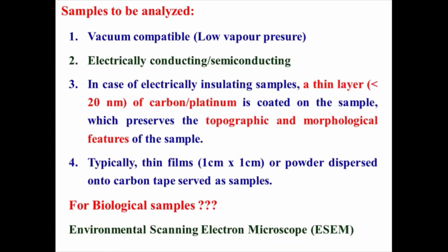So if you take a powder and it is not vacuum compatible, it may get evaporated, or the particles may get taken away by the vacuum pumps, or if it's a biological entity containing water or some liquids, then it may get dehydrated. So these samples you cannot use.